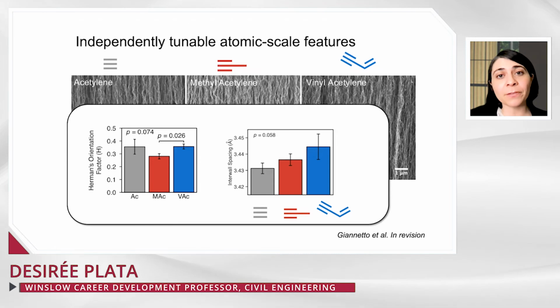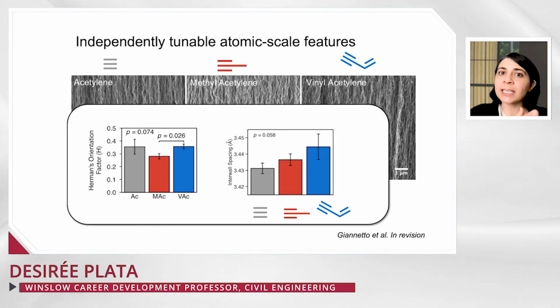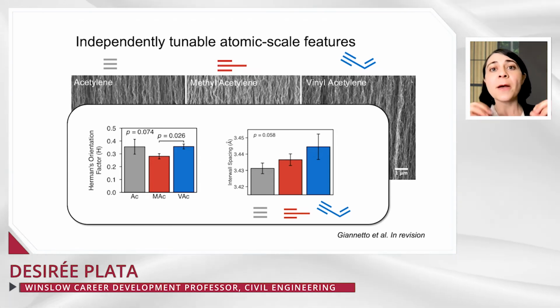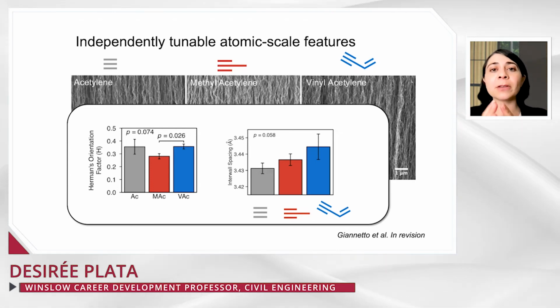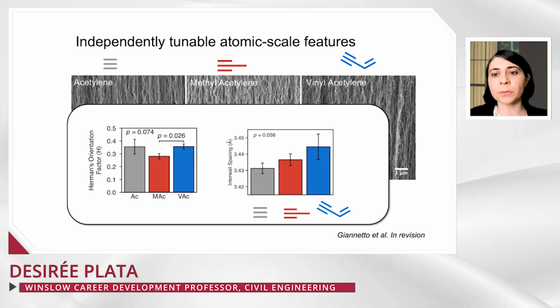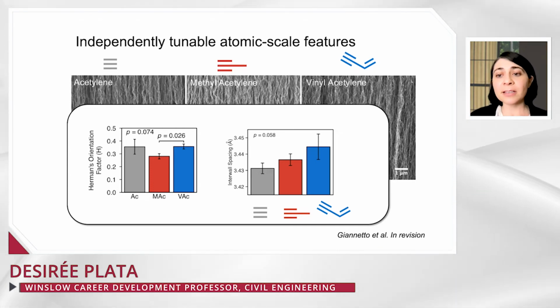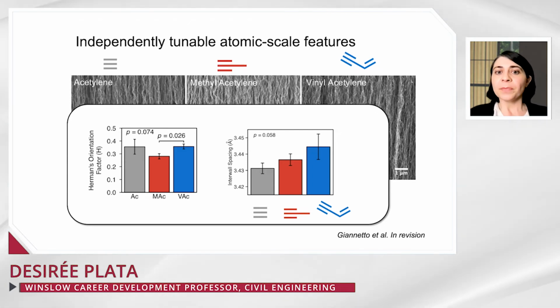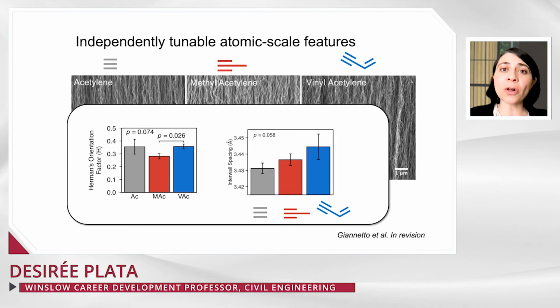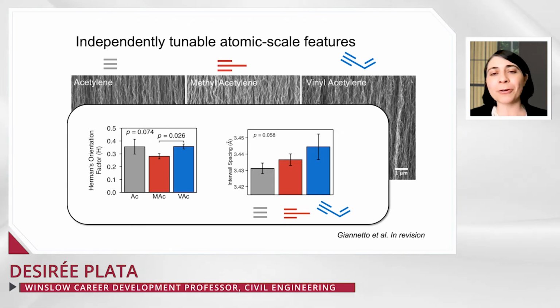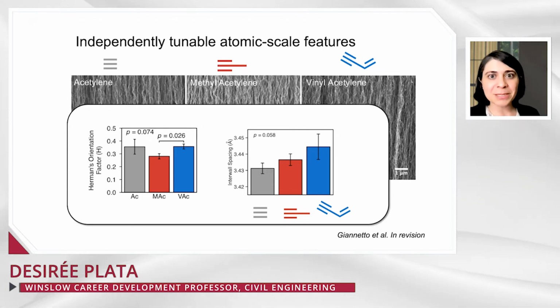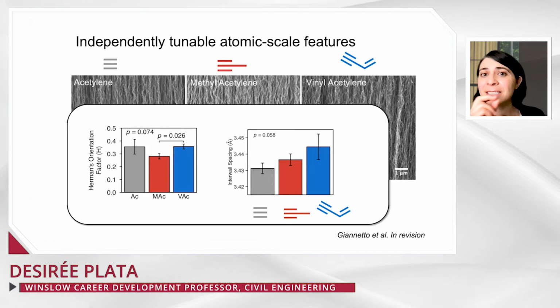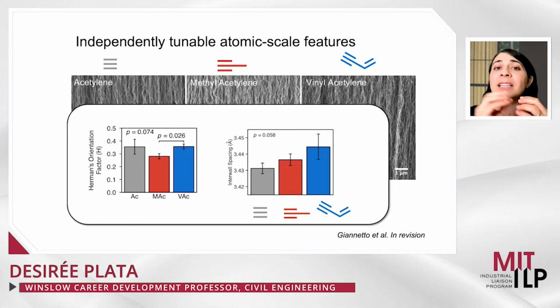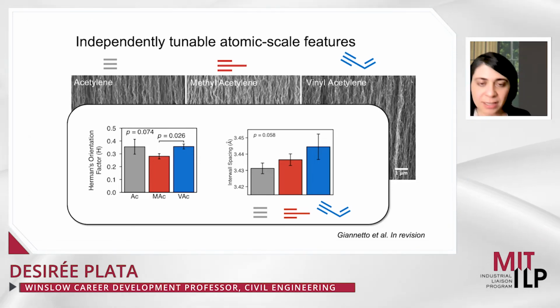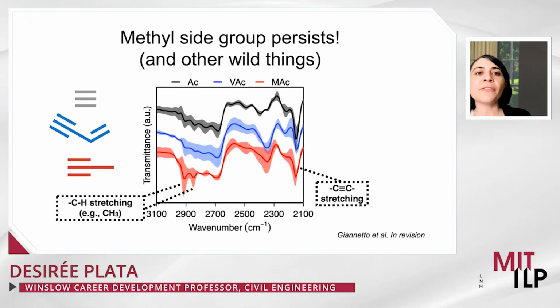The interwall spacing, on the other hand, the spacing that exists between concentric nanotubes, was tuned in the way that you would anticipate if those side groups were persisting. So acetylene has the smallest interwall spacing, whereas methylacetylene, where you have to accommodate a methyl group, has a slightly larger interwall spacing, and vinyl acetylene has a larger still interwall spacing. This is a remarkably conserved number in nature. The interlayer spacing of all graphitic materials occurring in nature is 0.34 nanometers. And we see that same measurement here with slight variations to accommodate those side groups. This was a really remarkable finding.